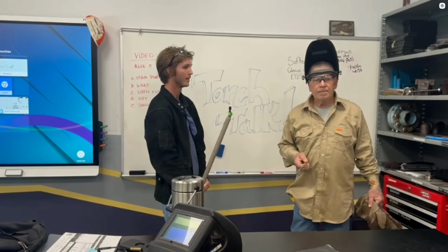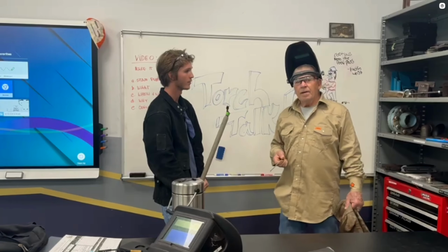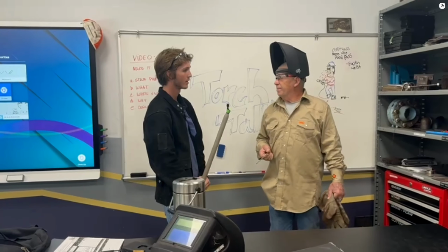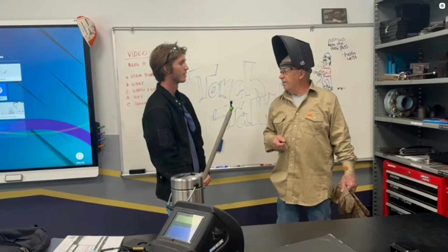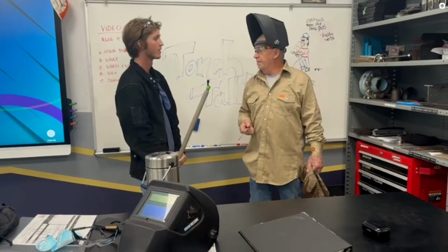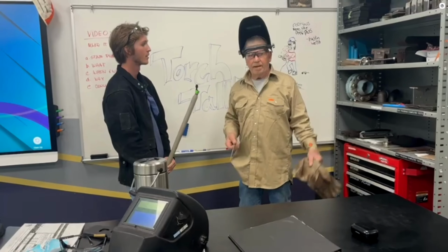So to sum it up, fast freeze for penetration and position welding, fast fill for heavy flat welds, fill freeze for general use, and low hydrogen for critical high strength applications.